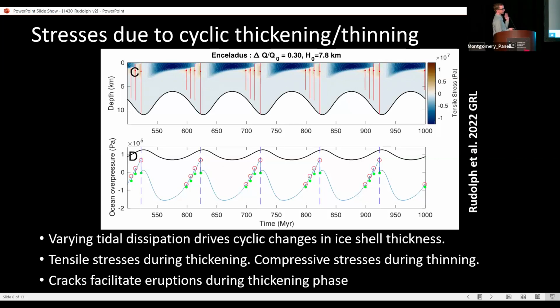And the top panel shows stresses as a function of depth. Blue indicates compression, red indicates tension. And you can see that as the ice shell gets thicker, there are tensile stresses generated. As the ice shell gets thinner, compressive stresses are generated.